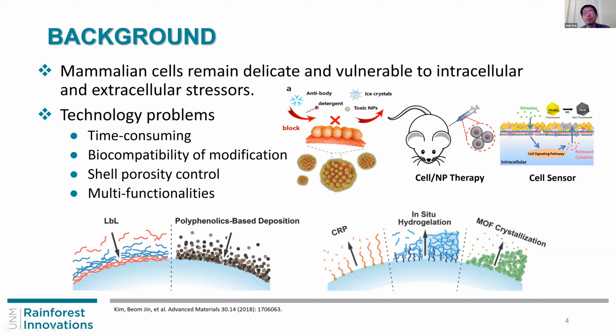At the same time, since we have the nanoparticle on the surface, we can use the nanoparticle itself as a sensor, to sense molecules released from the cells as well. Compared to the regular techniques, typically people do encapsulation of the cells. They do layer by layer polymer, or phenolic acid deposition, or other polymer growth, different ways, and also mineral crystallization growth on the surface. All of them are typically time consuming, taking hours.